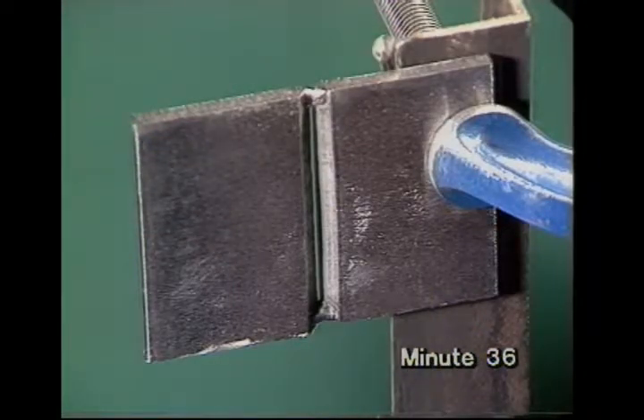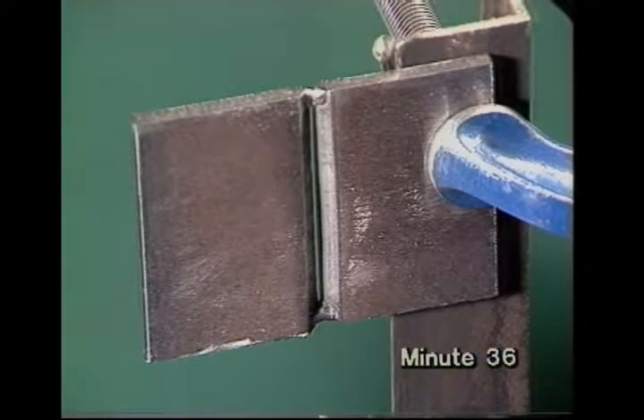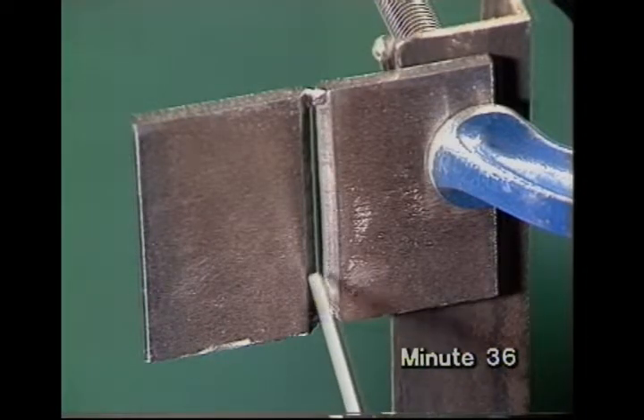A similar butt joint in thick metal to the one welded flat is prepared in the same way and welded upwards. If Max sees the edges start to burn through, he slows down, weaves and flicks the electrode to regain control of the molten metal. Looking from the back, we can see how the weld just penetrates the joint. The weld is completed by the usual weaving runs.